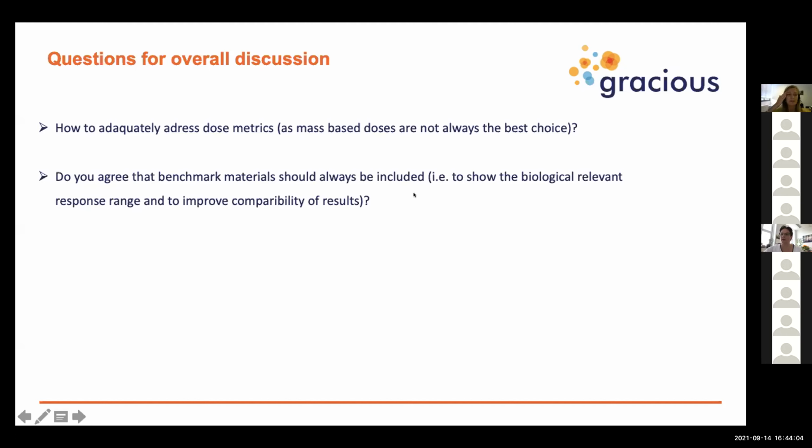Andrea, I sometimes think that the surface area metric is an important one, and it has a number of connotations. For dissolution, the rate of dissolution is going to be related to the surface area per unit mass, but also surface reactivity as well. So the surface area metric needs some careful consideration. I think you need to first ascertain whether you're looking at something that's very slowly dissolving or something which is rather quickly dissolving, and then you can make your consideration of dose metric and how it influences your data interpretation based upon that, perhaps.